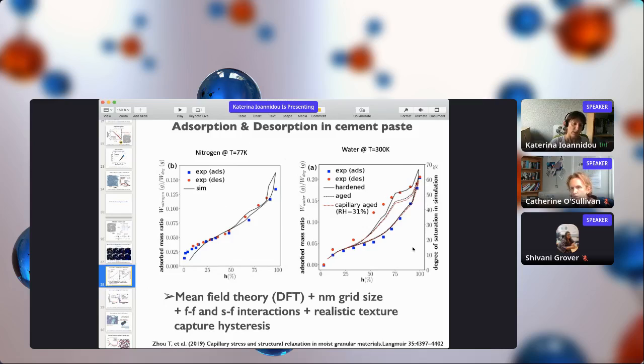But the important thing is that we need a realistic texture for cement. So we need a texture that has a pore size distribution that is realistic, and connectivity of the pores that is realistic. We need to calibrate the fluid-fluid and fluid-solid interaction appropriately. And a very important point is that we need the grid size of the simulations to be nanometric. So this is the expensive part of this computation.